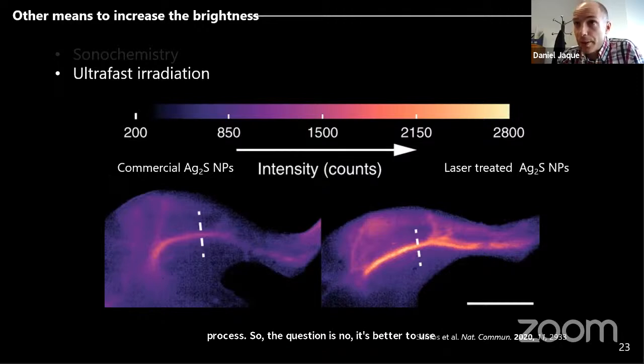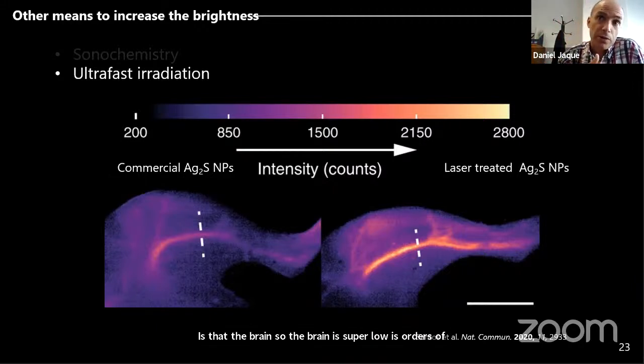But what is the problem with rare earth doped nanoparticles? Is that the brightness is super low. It's orders of magnitude lower than these nanoparticles. So in terms of stability and reproducibility they are better. Also the spectral quality is better, but the brightness is a nightmare. I mean, it's very hard to work with rare earth doped nanoparticles.